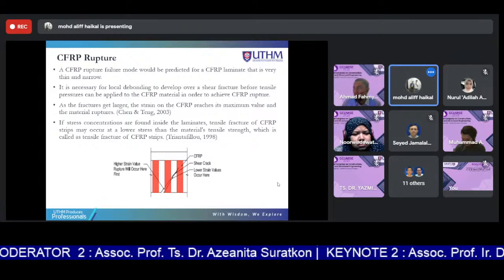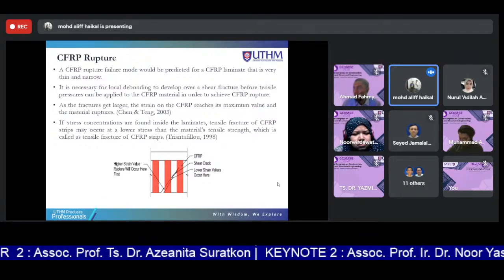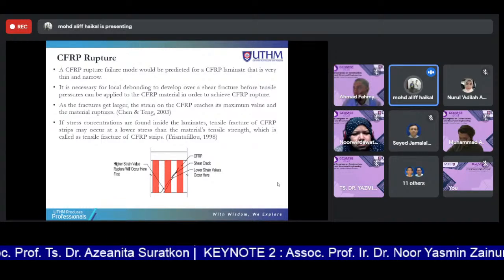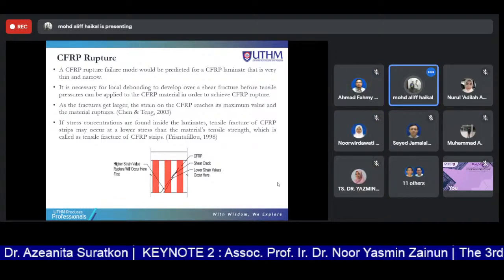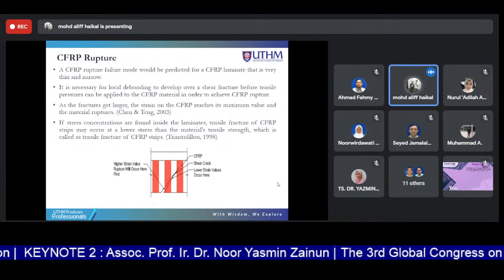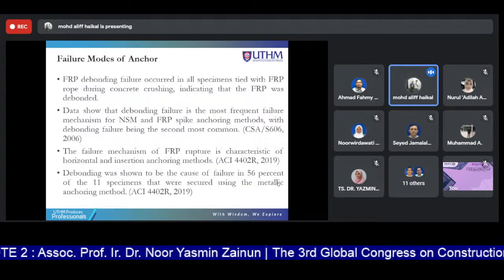If stress concentrations are found inside the laminate, tensile fracture of the CFRP strip may occur at a lower stress than the material's tensile strength, which is called the tensile fracture of the CFRP strip.